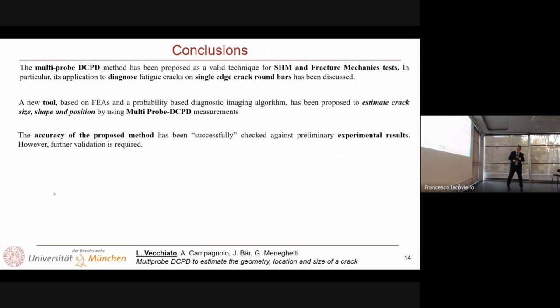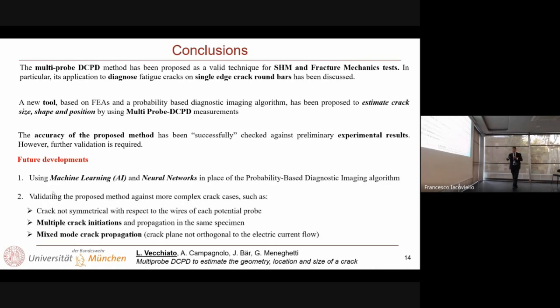So I'm done. I'm going to the conclusions with this simple, preliminary exercise. We have shown that we can use the potential drop in a different manner for measuring cracks inside material. And we have applied this method to single-edge simulated cracks on round bars. And we have more ideas than time. We are actually improving this technique, just switching from the probability diagnostic imaging algorithm to machine learning, just to be more mathematically rigorous, let me say like this. But we want to work with multiple crack initiation, different crack geometry. We have many ideas about that, and for sure 3D problems of mixed mode crack propagations.